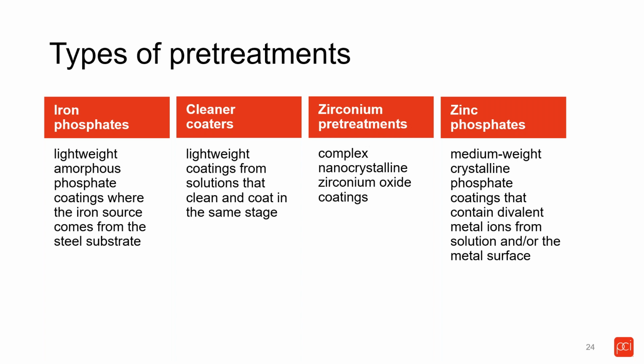One of the most important things about a zinc phosphate system is that you need a grain refiner stage before the zinc phosphate itself. Otherwise you will lose the tremendous corrosion protection it provides, because the crystals will be a lot bigger and a lot more brittle. You can see a lot of adhesion loss, and there might be certain spots where you don't have a coating, which will completely affect your corrosion performance. So you want to make sure your grain refining rinse is running at an optimal level.